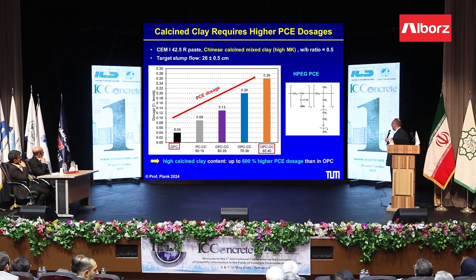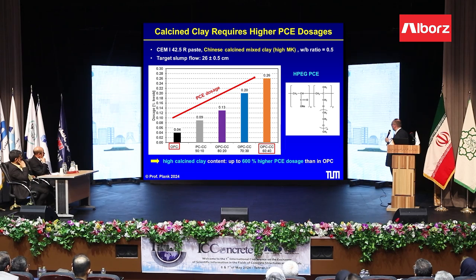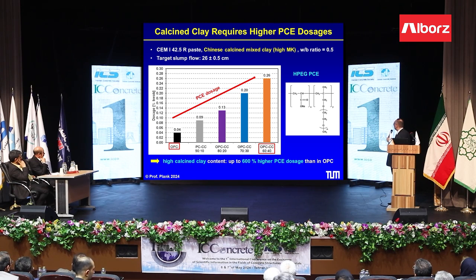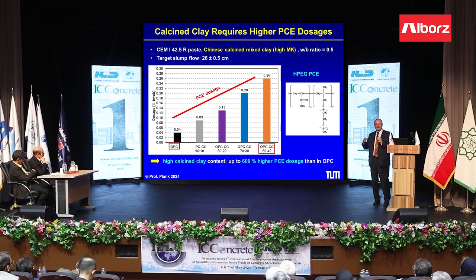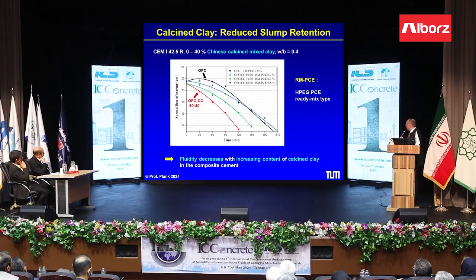Now, a commonly known problem of calcined clays is that they require much higher PCE dosages. If we substitute OPC with calcined clay more and more and more, you see the PCE dosage goes up very much. Here we use the HPEG PCE, and especially here where we used a calcined clay from China with a high metakaolin content. If the metakaolin content is high, then this calcined clay needs very high PCE dosage, and obviously this is not very good because it increases the cost.